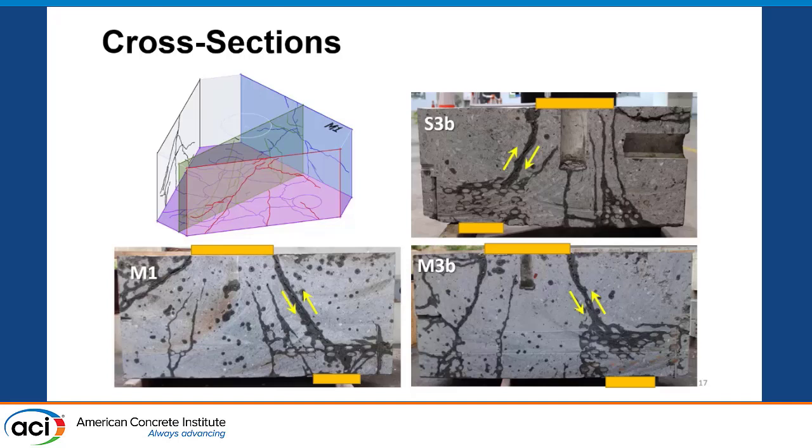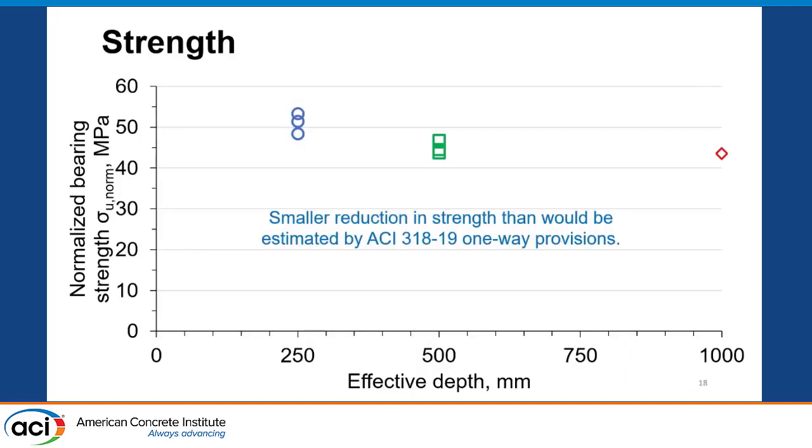We actually ended up doing projected views in SketchUp on these to try to understand what the three-dimensional crack patterns look like in these specimens. What we observed in general was an initial punching of that top platen, followed by a sinking and relative deformation of these two zones here. So just an example of one of the observations that we had from the tests.